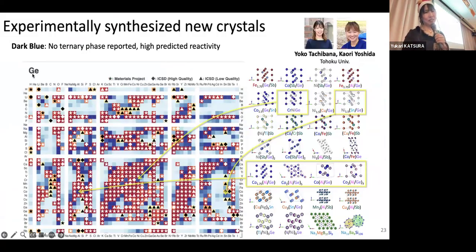So go back to the germanium map. When we synthesized this combination, germanium, aluminum, and cobalt, we succeeded in getting 4 new phases. So these are new combinations. The structure is known. This structure originates from cobalt germanium, and these are solid solutions. We are having many solid solutions just because XRD analysis was easy for solid solutions.